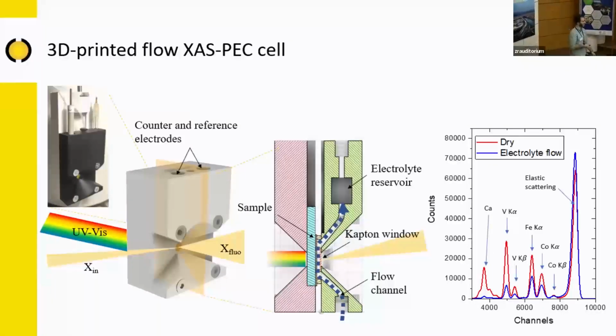We had to face several issues, and we designed the cell to address those issues with these specific samples, because as I told you, we have thick samples, we cannot work in transmission, but we still need to have light illumination on the sample. So we designed it to be possible from the back of the sample. So we have the light impinging on the sample from the back.